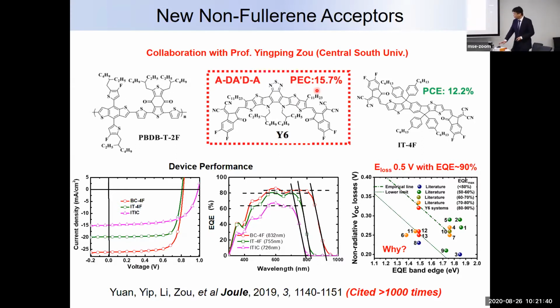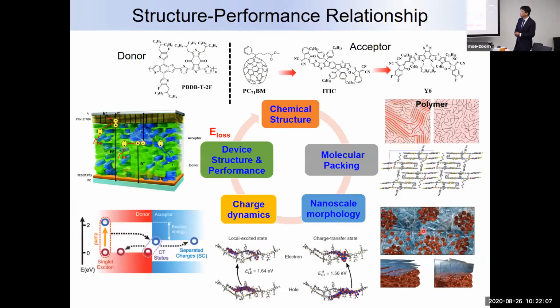And we also find that the red dot here corresponds to the non-radiative VOC loss. We try to keep it small. So this Y6 material has a relatively small non-radiative VOC loss, particularly when you consider that it still has a very high external quantum efficiency, close to 90%. So over the past 1.5 years, my group has really been trying, based on this